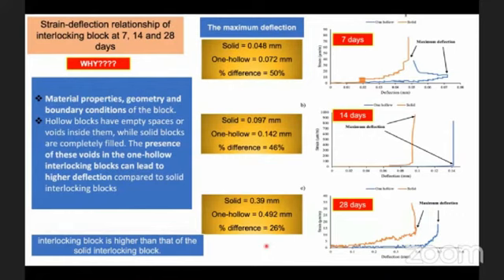This phenomenon indicates that the maximum deflection is due to the bending or sagging of the interlocking block under load, which is influenced by a variety of factors, such as the material properties, geometry, and boundary conditions of the blocks. The main difference between solid and hollow blocks lies in the geometry. And then I move to the next slide.